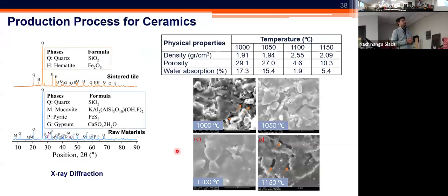One of the key questions when it comes to sintering of the material is the temperature at which you can apply the sintering effect. So we did explore different temperatures, starting with 1,000 degrees Celsius all the way to 1150. The challenge was to identify the optimal temperature for the successful ceramic production that would provide the highest density as well as the lowest porosity. If you do a comparison among the different temperatures that we explored, clearly you see that 1100 was the best performing because it provided us with the highest density as well as the lowest amount of porosity for these materials. So we adopted that for the production.